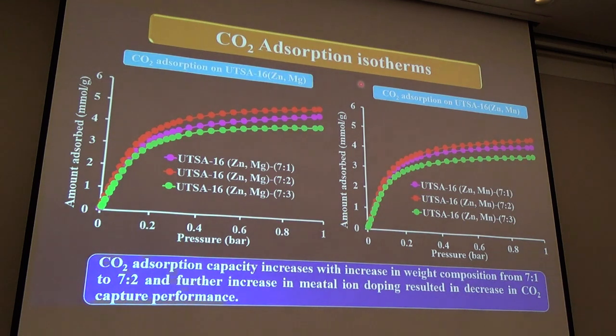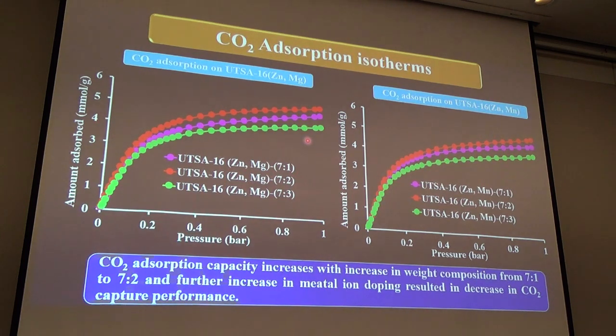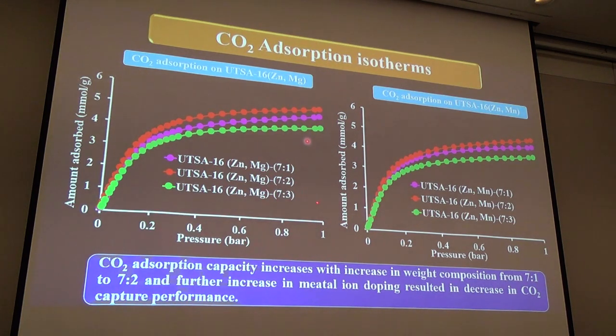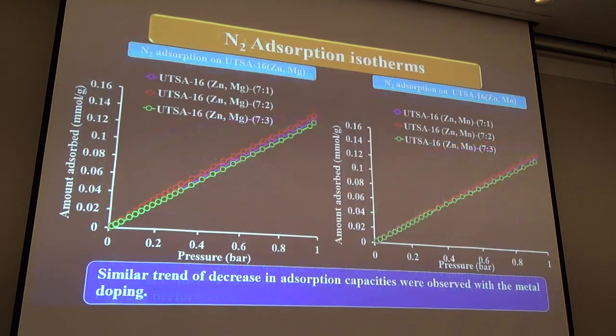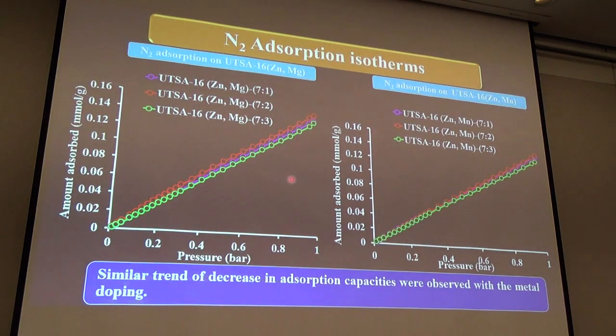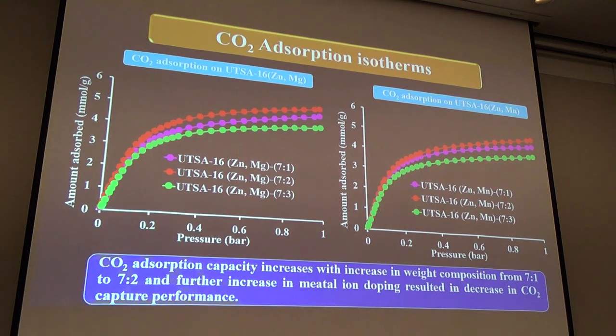CO2 adsorption capacities. CO2 adsorption capacities were measured at 1 bar and 298 Kelvin. As we see in the figure, CO2 adsorption capacity initially increases with the increase in metal ion doping. However, excessive amount of secondary metal ion leads to a decrease in CO2 adsorption capacity. This increase in CO2 adsorption capacity may be attributed to the increase in surface area and open metal sites generated by solvent removal and heating process.